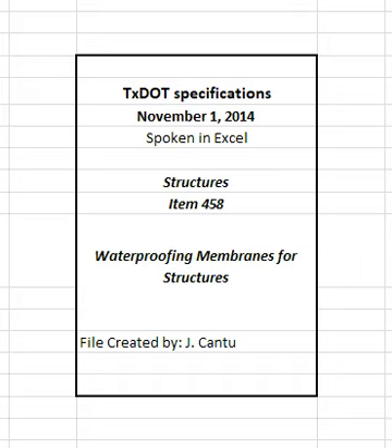Offset the vertical joints of the second layer at least 4 inches transversely and 1 feet longitudinally from the joints in the lower layer when 2 layers of planks are used to obtain the required 1 inches cover thickness. Apply asphalt mat protection in the same manner except stagger the longitudinal butt joints in a single layer by approximately 2 feet. Follow the same procedure with all vertical joints offset by at least 1 feet. When more than 1 thickness of asphalt mat is required, place a follow-up coating of asphalt emulsion approximately 6 inches wide over all joints of the top layer.